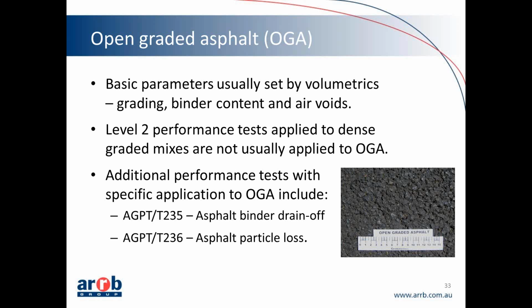Yes, well, the next thing we were going to talk about is open graded asphalt mix design, because as Laszlo said at the start of his presentation, the design procedures are basically developed around dense graded mixes, but we do need some variations for other types of asphalt mixes. And when it comes to open graded, there's no universal rational design procedure for open graded asphalt. Basically it's the volumetrics, which are grading, binder content and air voids, which are the primary design requirement. The level 2 tests that are applied to dense graded mixes generally are not applied to open graded asphalt.